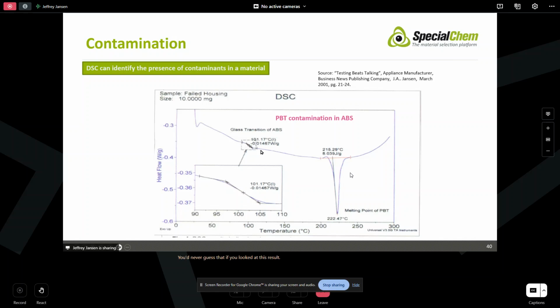Here's our glass transition, looks relatively weak. Here's our melting endotherm, looks pretty strong. You'd guess that this is mostly PBT, perhaps with some ABS contamination, but it is the opposite way around. The good news is that contamination just stands right out. It jumps out at you. So you can identify, in some cases, contamination in materials.